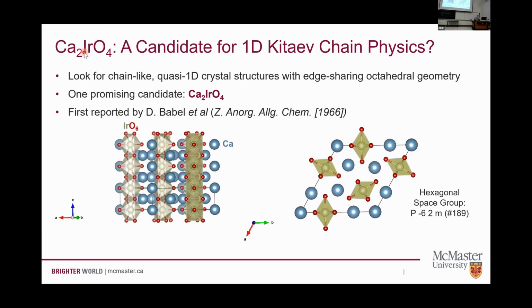It seems to have everything that we want. So it's got the iridium, that gives it strong spin orbit coupling. It's got this quasi one-dimensional chain-like structure, which is edge-sharing iridium-O6 octahedra that run along the C-axis. And so bond angles should be close to 90 degrees, which opens the door to some Kitaev interactions. If you look down at this from above, you'll see that these octahedra are sort of aligned in this kind of pretty pattern here. Spacing between these is fairly large compared to the spacing along the chains. Right? So this looks like a great place to start.